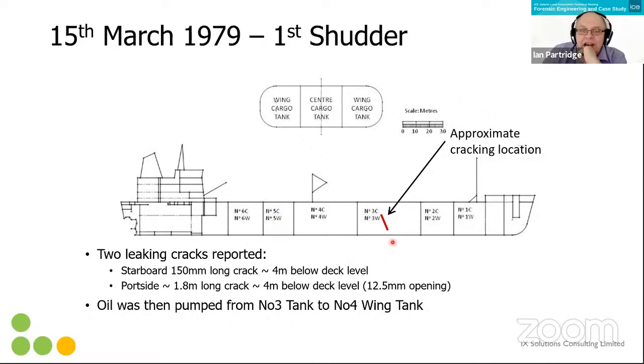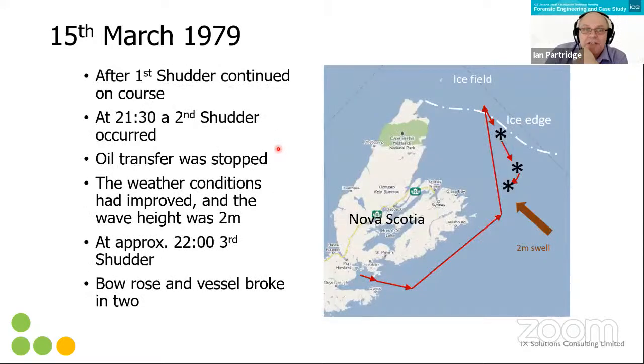On the port side, more obviously, there was a 1.8 meter long crack, roughly 4 meters below the deck, and it was about half an inch wide. Oil was coming out of this crack. There was one on the other side, slightly smaller. So they pumped the oil from the number 3 tank to the number 4 tank and carried on their way, trying to get back to port.